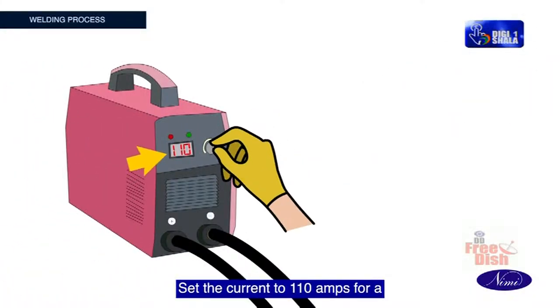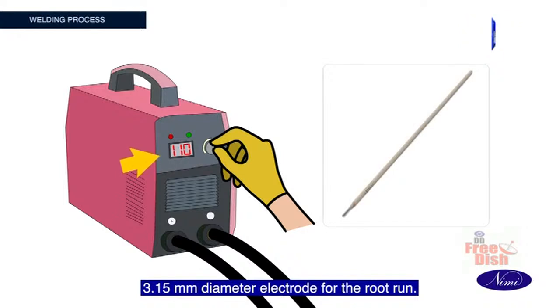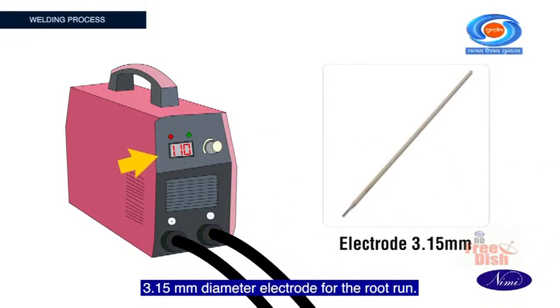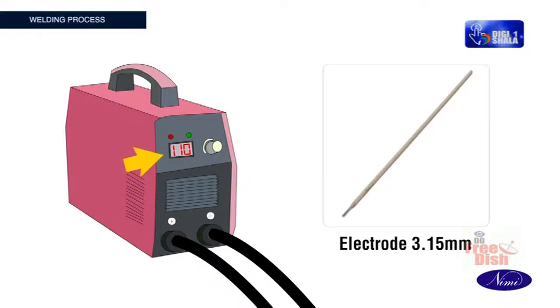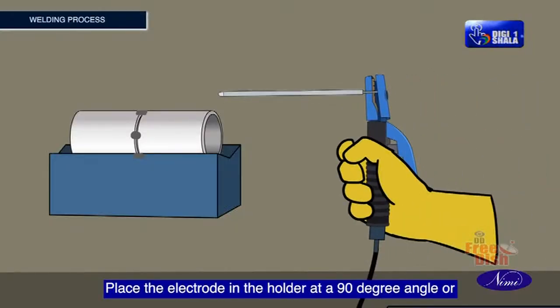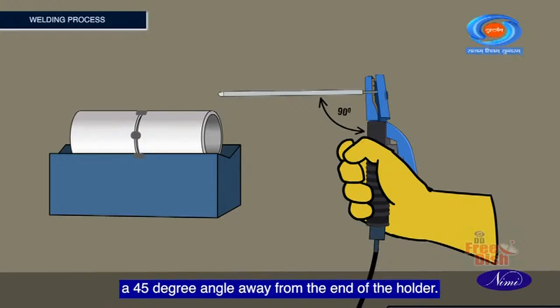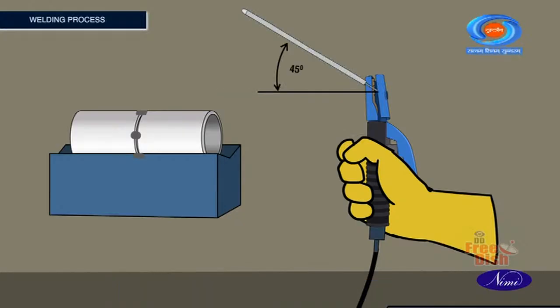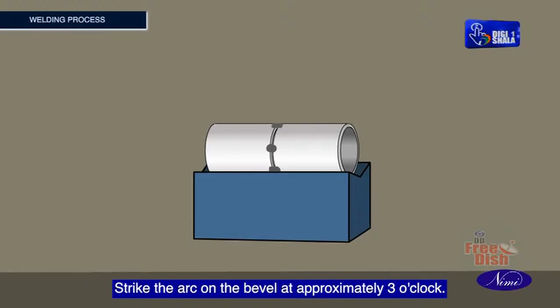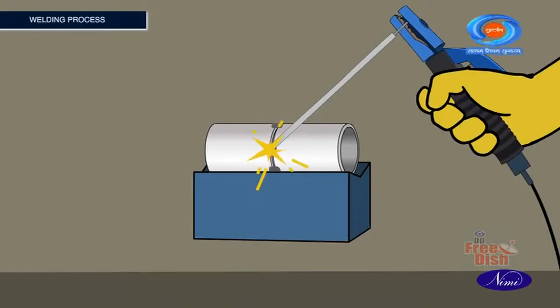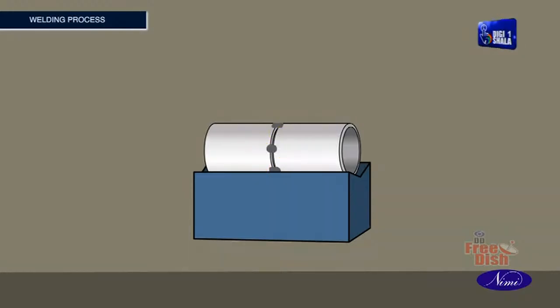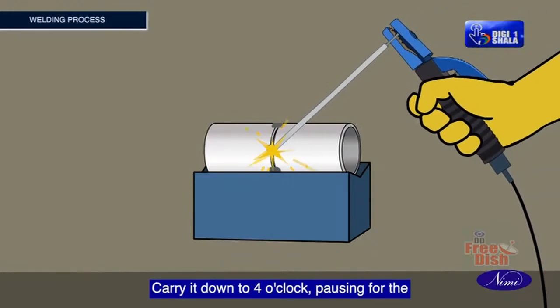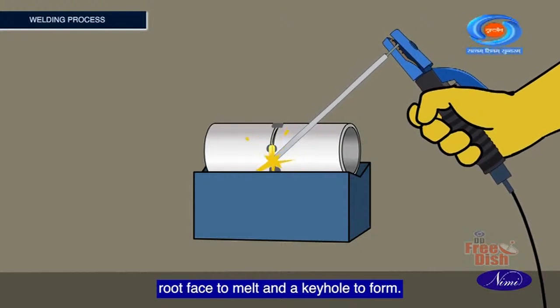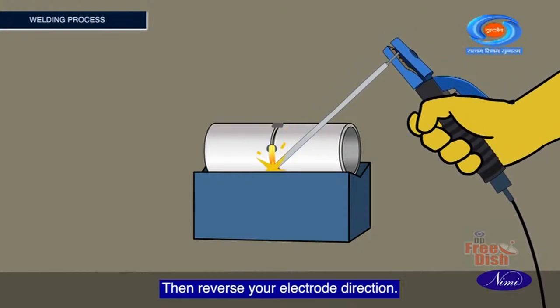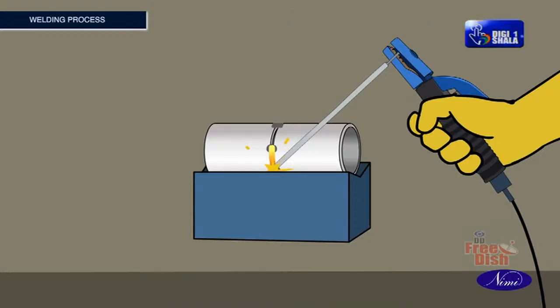Set the current to 110 amps for a 3.15 mm diameter electrode for the root run. Place the electrode in the holder at a 90-degree angle or a 45-degree angle away from the end of the holder. Strike the arc on the bevel at approximately 3 o'clock. Carry it down to 4 o'clock, pausing for the root face to melt and a keyhole to form. Then reverse your electrode direction.